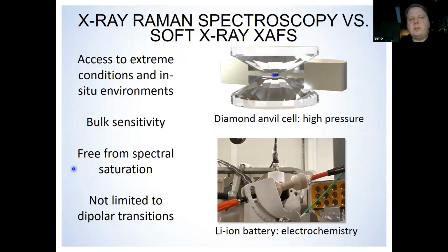Something that often is forgotten is that in XAS, those who are intimately working with it know that there are sometimes problems with spectral saturation, because the self-absorption can become so large that it has severe effects on the spectral shape. And actually, X-ray Raman is always free from this effect, which is also very useful. And it's not limited to dipolar transitions, and you can go back to yesterday's talk by Jerry on the different transition matrix elements. So diamond anvil cells, different kinds of in situ environments, you don't have to worry about that. Your X-rays go through most of the complicated systems, so you can do in situ electrochemistry, catalysis, hydrogen storage, many other things.